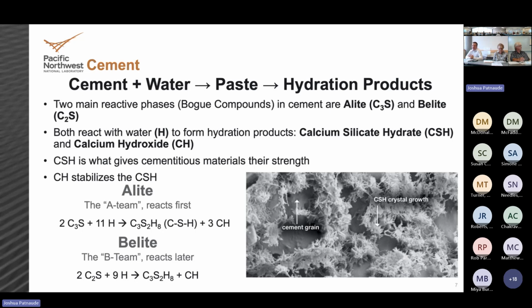And another product of it is you make Portlandite or calcium hydroxide. That's what makes cements have a higher pH. And that high pH environment is what chemically stabilizes the CSH. So the two products that you make, one gives strength and one kind of acts as a protectant. Okay, so we go to the next slide.